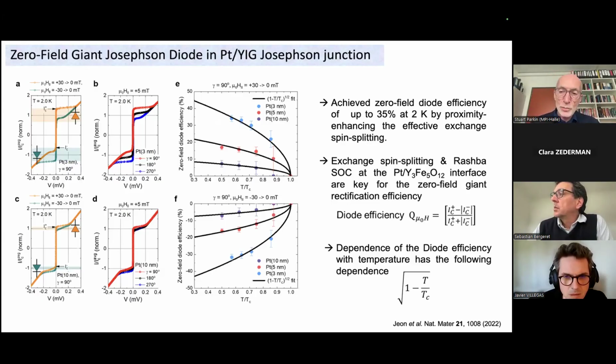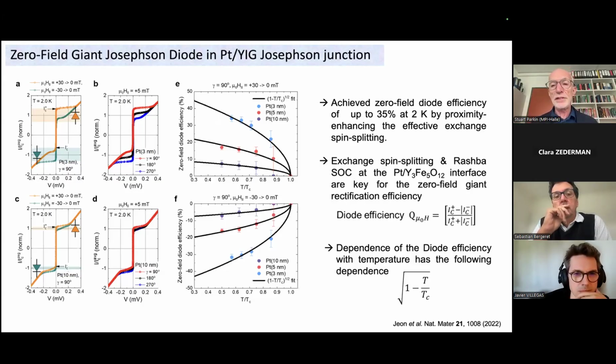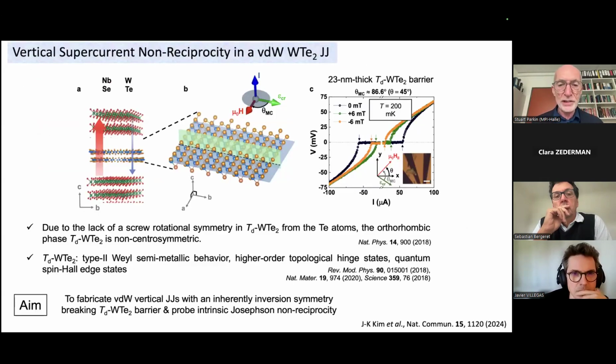In this case, also, we see very large effects. We see up to 35% difference in critical currents at now a higher temperature, 2 Kelvin. Previously, our work was at 10 millikelvin. So these are two very interesting proximity effects working together.